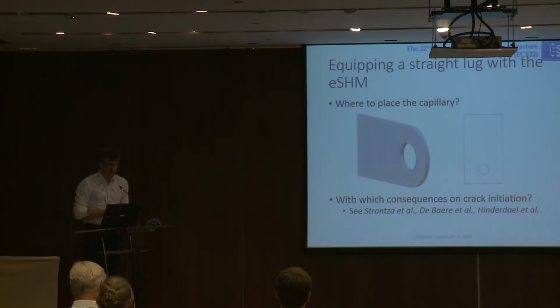And furthermore, as we are in Serbia, I decided to inspire myself from the work of Serbian authors, and particularly the author is here. I thank her very much again. So I've taken exactly the same load case as her, namely a straight lug with an axial cyclic loading. And of course, when you want to fit such a lug with the ESHM system, the first question to ask is where to place the capillary. And of course, the answer is close to the regions where you have a high risk of crack initiation. And in that case, it's around the pin lug connection.